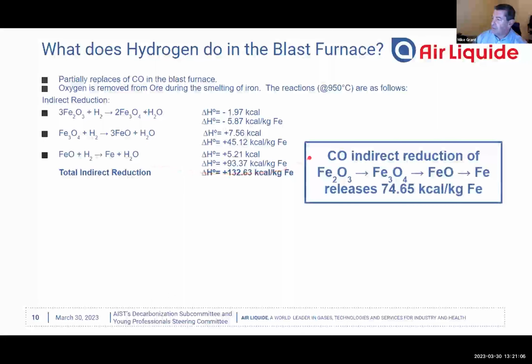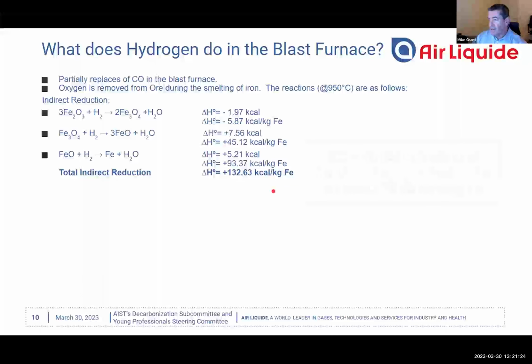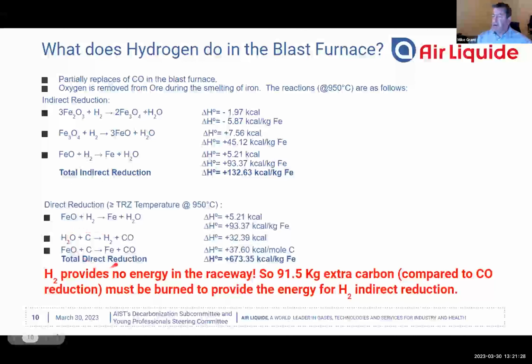If we compare that to CO indirect reduction, CO indirect reduction is actually exothermic, so it contributes energy to the process and therefore helps reduce the total energy requirement of the furnace. Looking at the lower part of the furnace, we start to react water with coke. This is highly endothermic, and the total direct reduction is a very endothermic process. So the net effect of hydrogen reduction in a blast furnace is equivalent to roughly 90 kilograms of extra carbon that needs to be charged to cover the endothermic nature of these reactions.